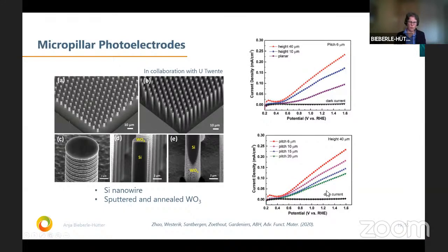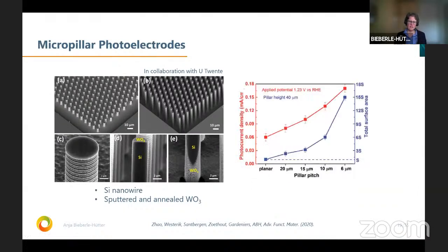And if we go to smaller pitches, we get also higher current densities. But actually, we are not so happy with it, because it's not as good as we expected it. And this is what you see here a bit. So we see here when we increase the total surface area, we get a strong increase when we go down in pitch. But the current density does not increase as much as we expect this.